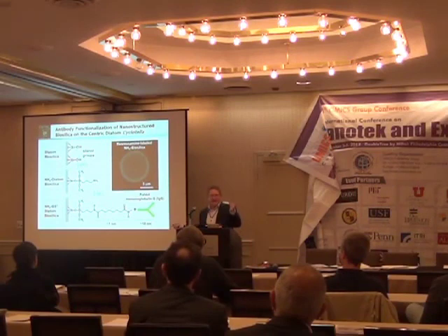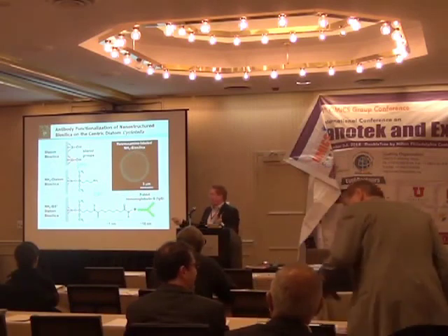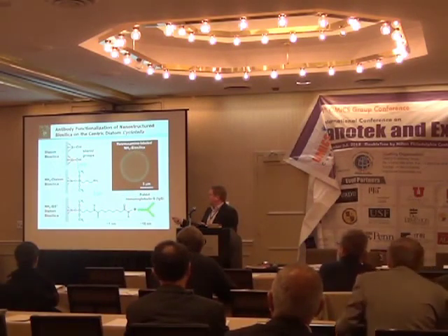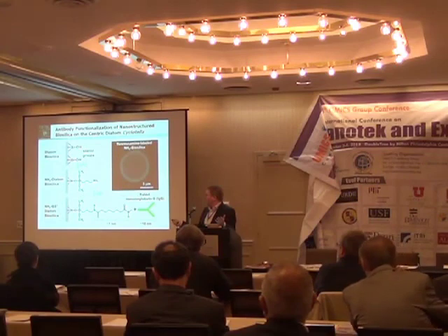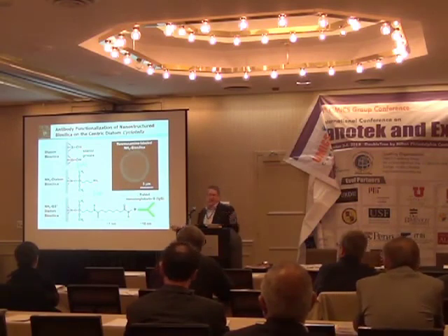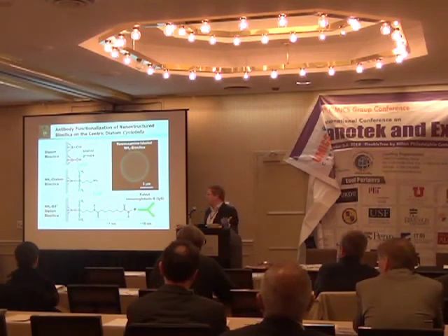Unlike glass, biogenic silica has a lot of silanol groups because it's an amorphous material. So it's readily functionalized to have an amine functionalized surface, in this case through aminopropyltriethoxysilane. And then with those reactive amine centers, you can use a common biomolecule protein cross-linking reagent.